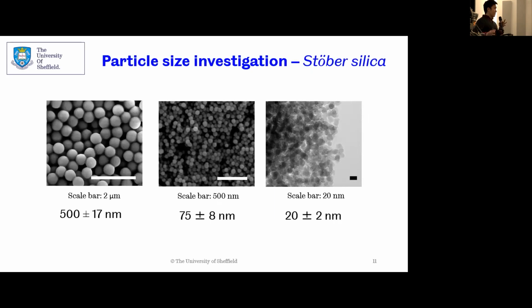So the materials chemists among you, this is a solid state reaction. So it's diffusion limited, which means the particle sizes would affect, amongst other things, how quickly it reacts. So here it is. I made silica particles using the Stöber method at different sizes. This is a well-known method. You can make uniform silica at 500, 75, and 20 nanometers, and then I reduce them with magnesium at different temperatures.